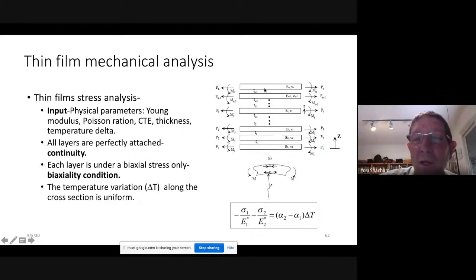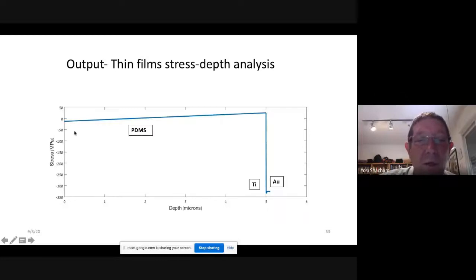that we can calculate the stress in this material, and because we want to deal with more than one layer, we develop it. This can be polymer, metal, so we solve it for multi-structure. And then we apply this solution to calculate the stress in our materials. So this is stress versus depth. This is a PDMS, about 5 microns.